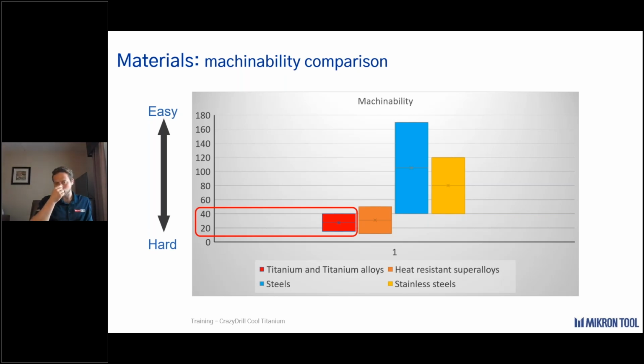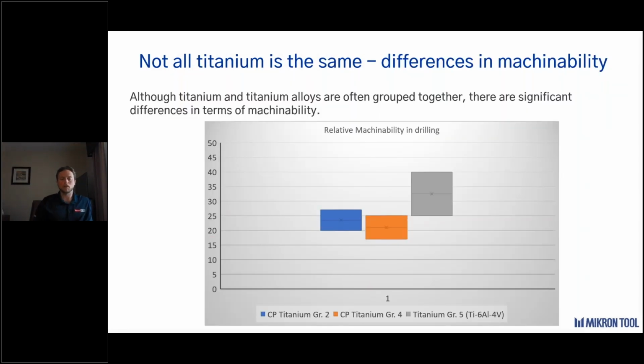What's interesting about titaniums, though, is they fall into even a little bit of a subset category. Not all of the average machinabilities for every type of titanium falls directly in the line that we see. We end up separating these two into the most common categories of titanium. Commercially pure titanium, or CPs, those are typically going to be your grades under 4, so 1 through 4. Then you have grade 5 and above. These are going to be our alloy titaniums. Typically, the alloy titaniums have a little bit greater strength, right, due to their alloyed components, and a little bit better machinability. Looking at it from a drilling standpoint, you can't have one geometry parlay across a family of titaniums.